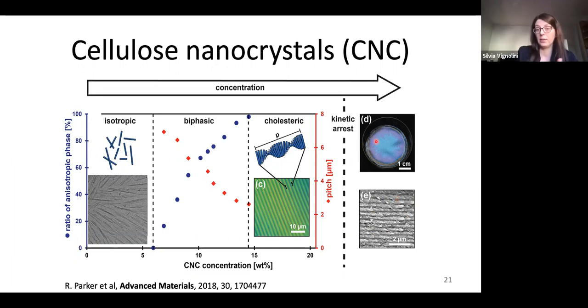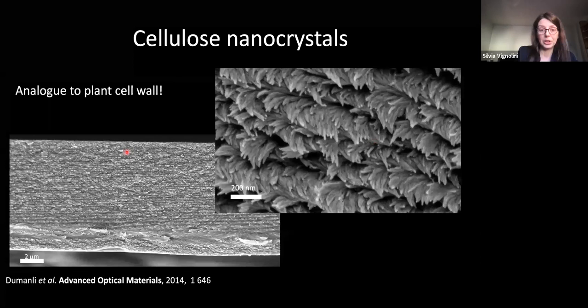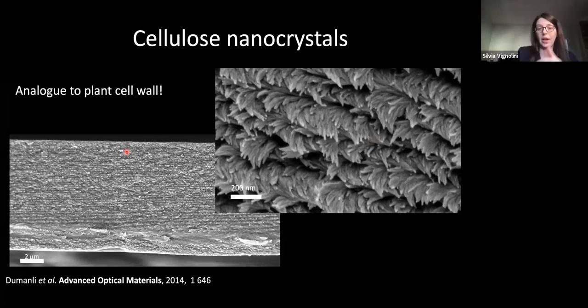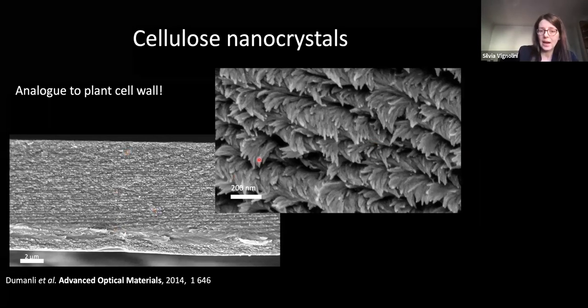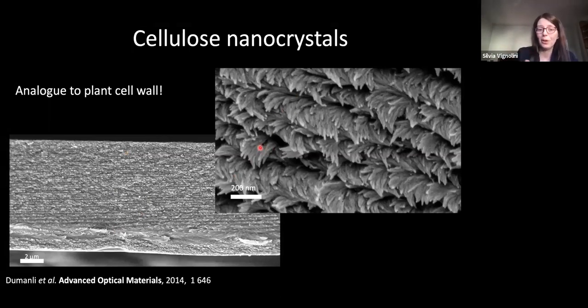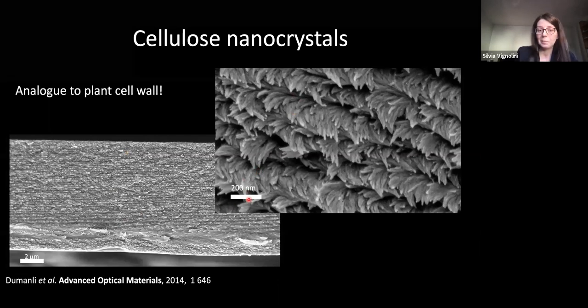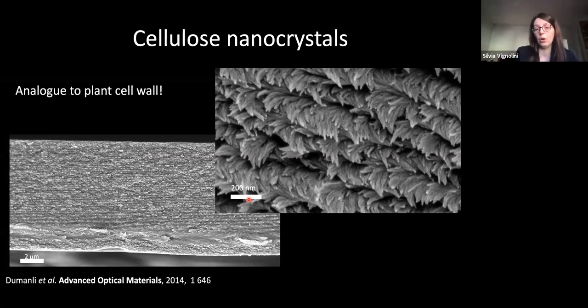And in fact, you can get colored film. Let me show you a little bit with a higher magnification. If you look again in cross-section of the film that I just showed you, you can recognize this layered structure where you can really see the cellulose crystals, like in the case of the plant cell wall, on the same length scale that provides this blue coloration. So essentially, you are able to make color out of the same material that you have in your paper. Yeah, this is essentially the concept behind our work.